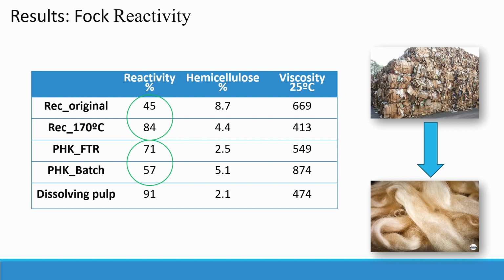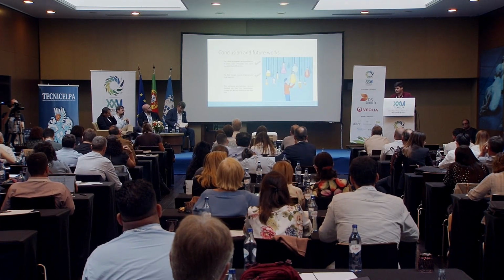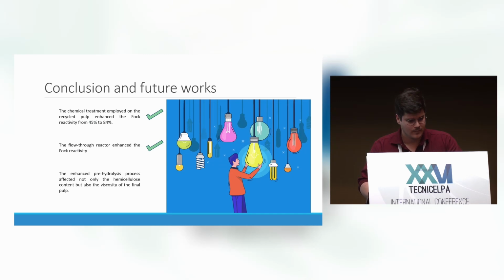Regarding the flow-through, as we saw before, it's a pulp with higher purity, and this translates into a higher reactivity. They're still a bit far away from the commercial dissolving pulp, but it's a method we need to optimize. And this is the future work. One of the interesting results was the increase in Fock reactivity in the recycled pulp, so we can produce pulp from an end-of-life pulp, and we can enter the circular economy with this type of pulp.